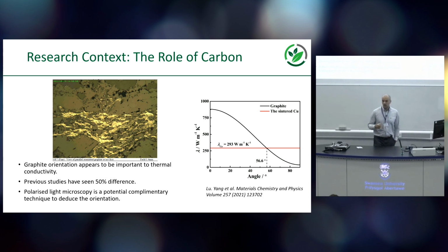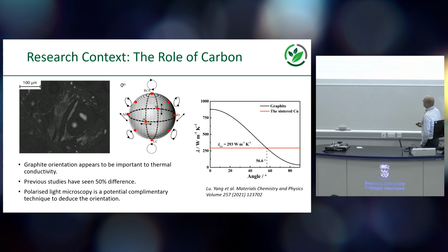And that's quite interesting on its own, right? Because it aligns in different directions. So depending on how you've pressed the brick, you can align the graphite in different directions. And if you look at learnings we have from other composite structures, so this is graphite in copper wires, from an electrical perspective, you can see that the orientation of the graphite has a massive impact on the conductivity of the material.